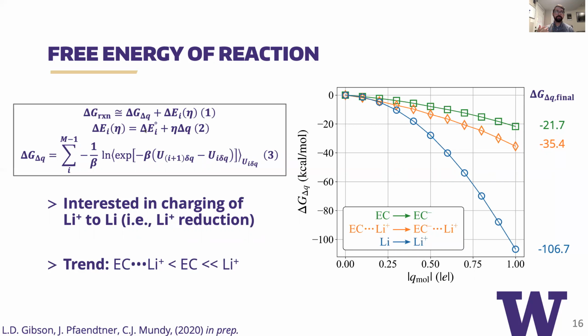your difference in electronic states, electronic energy levels, rather, which includes your electron affinity of your acceptor and your ionization potential of your donor. But we also have the second term, which is this overpotential term, which has an external bias that raises your Fermi level, which ultimately affects your free energy of reaction. And then we have this third equation, which describes your change in solvation free energy.